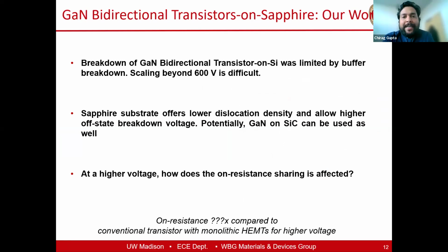So once we did that, we realized that, of course, we are limited by silicon buffer breakdown. And if we want to make a real device out of it, we need a lot of margin, and so on and so forth. So scaling the voltage beyond 600 to 900 volt is obviously going to be very difficult. One of the solutions that we thought was, why don't we switch to sapphire substrate? Because with sapphire, you get slightly lower dislocation density, and sapphire is an insulating material, so the vertical breakdown may not be an issue, and we can push the breakdown voltage to higher voltages.